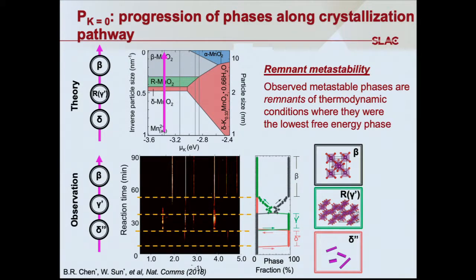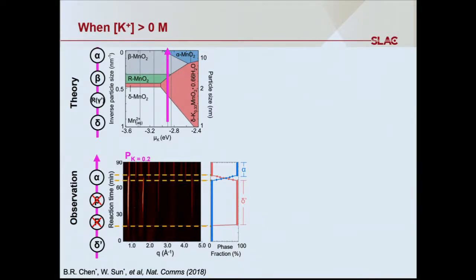And anytime you would interrupt this, you would make a metastable phase, right? If you say, I'm going to interrupt it here, I would have formed this metastable phase, right? Okay, then I'll show an example that's a little more complicated. So we now go to a higher potassium chemical potential. So now you would expect to go manganese 2 in solution, then you cut into this red region, which is the birnessite, the delta phase.